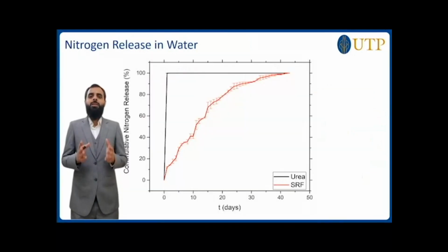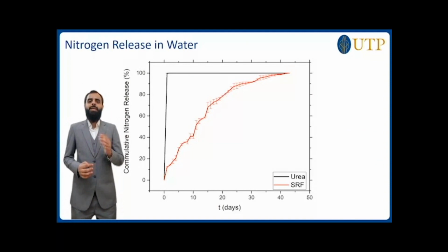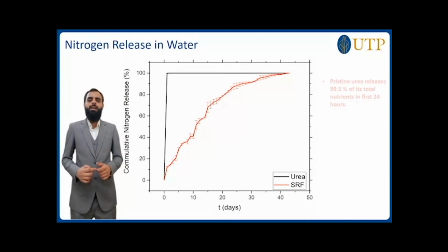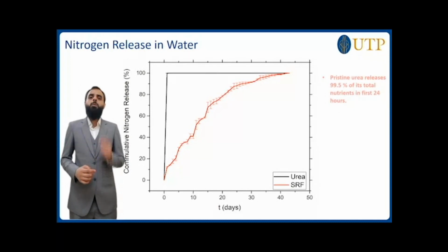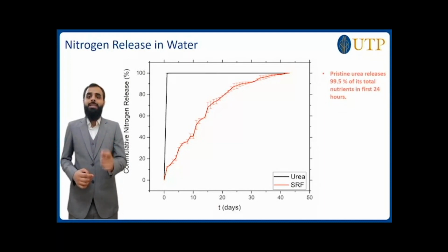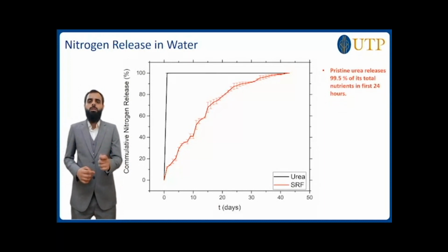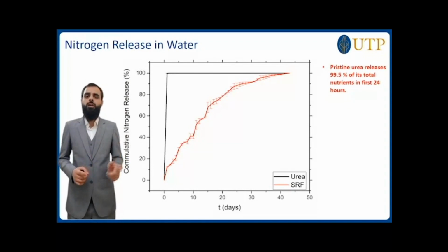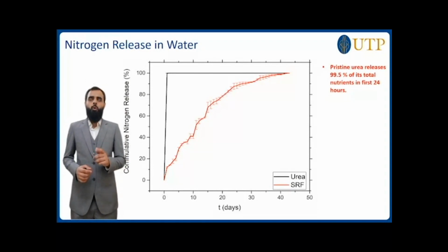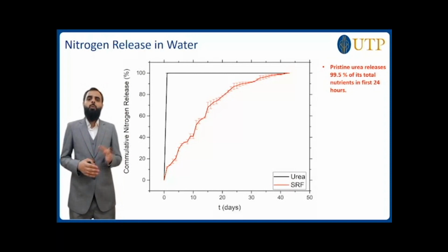To test the nitrogen release longevity of our produced fertilizer, we did a nitrogen leaching test in distilled water. Firstly, we calculated the total nitrogen content of our produced fertilizer using the Kjeldahl method. After that, we placed 2 grams of our fertilizer in 200 ml of distilled water in an aluminum flask placed in an incubator shaker at a speed of 220 rpm. A similar experiment was repeated for pristine urea as a control experiment.